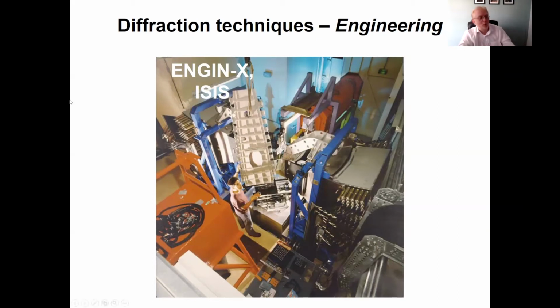And we can do this on wings, we can do it on railway lines, we can do it on jet engines, and we can investigate a whole host of things like how does tensile stress influence the diffraction properties in the surface stresses and strains, which are very important for failure of welds, but also for corrosion processes and many other industrial things where things are actually being used, and how does the actual use influence that surface diffraction.